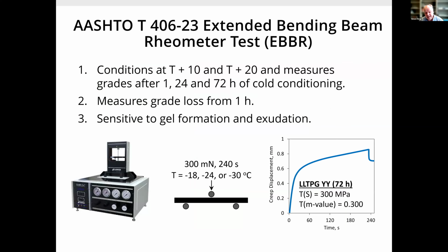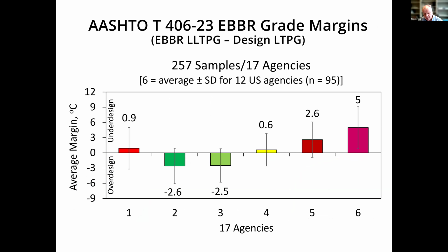I've tried to convince people that you cannot just test after 1 hour conditioning. No, you need to condition for 24 and 72 hours, and then you look at the grade loss from the 1 hour result. This test is extremely sensitive to the formation of gels and the sweating of those oils. But it's been an uphill struggle.